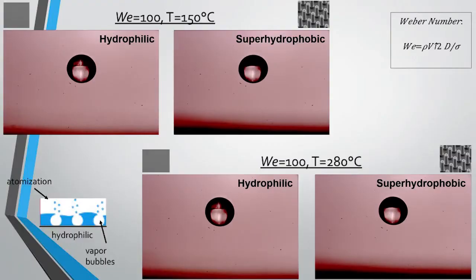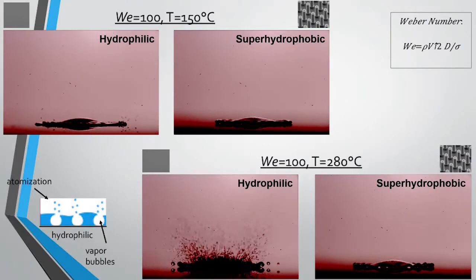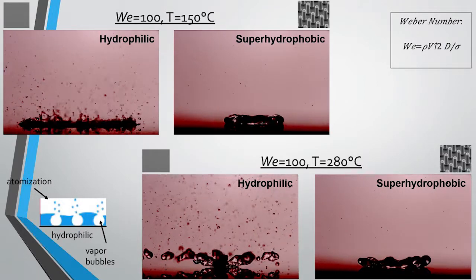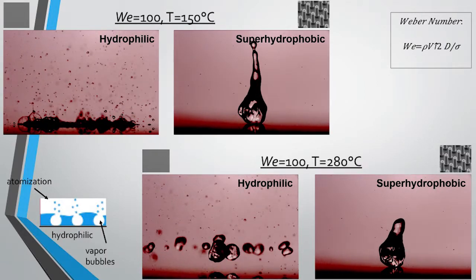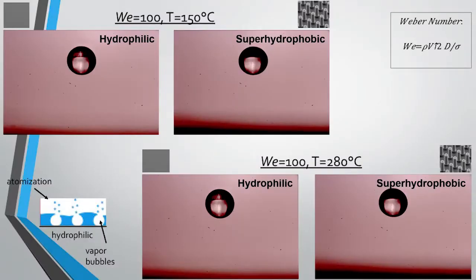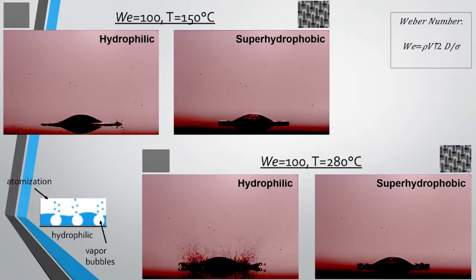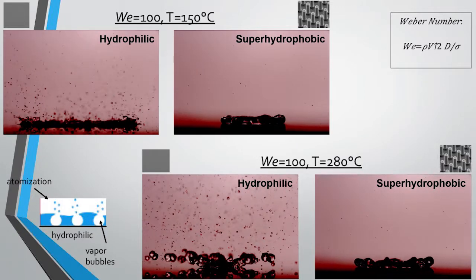Ours is the most exciting, of course, type of atomization, and that's where you have this violent boiling and the vapor has to escape somewhere. If I increase the temperature, the original temperature is 150 C, and the Weber number is just a relationship between basically how fast the droplet's hitting relative to how much surface tension is going to pull it back together. So how much it's going to spread versus come back together. As that increases, I have more momentum, so it's going to spread out further. And these are both the same Weber number, but as the temperature increases, you can see the hydrophilic surface gets pretty exciting. It goes into droplets, and then it separates, and all sorts of things happen.